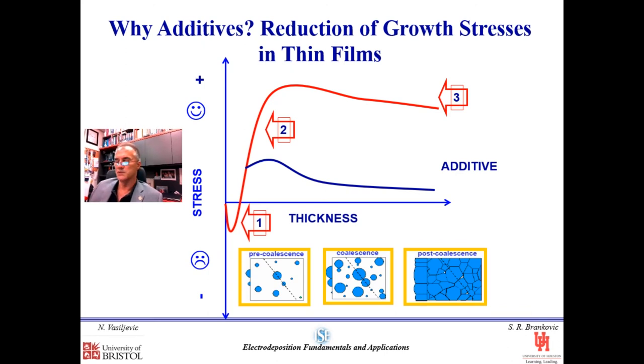then the stress suddenly drops down, which significantly improves the functionality of our coating or film, because the low stress levels mean you can go thick, you can do a lot of stuff with these coatings. If the stress levels are high, typically this results in thin film delamination and failure. So when we talk about corrosion protection, for example, chromium, that's one of the things that people need to worry about.